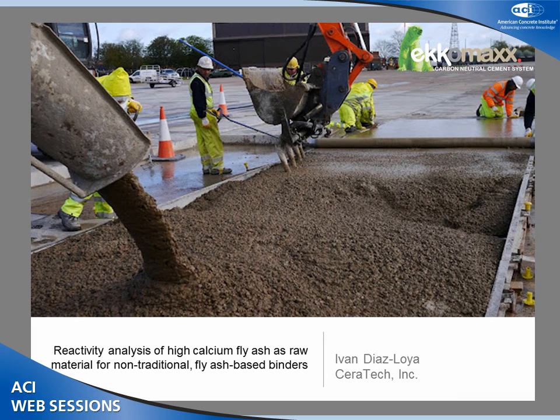Well, what I want to share with you today is just a small study that we did at CeraTech. I did this along with Carlos Orozco from Argos. We were basically looking for a couple of reactivity indicators for the fly ash that we use. We use high calcium fly ash, but basically we needed something beyond pass or fail.